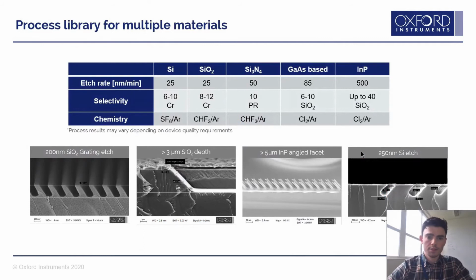This isn't limited to one or two materials, and here are some basic examples. Something like a silicon oxide etch, a deep silicon oxide etch, 3 microns with a slanted edge, towards a 5 micron angled facet, with indium phosphide there, and also isolated holes as opposed to a continuous grating shown in silicon.